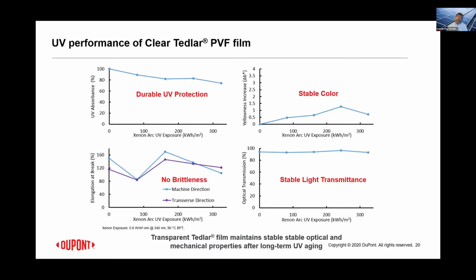So anyway, coming back over here, the film itself doesn't get brittle, again, over 350 hours of UV exposure, and it does not lose the light transmittance that I had shown you earlier over this entire exposure period. So this gives us the confidence that the transparent Tedlar film maintains stable optical as well as mechanical properties after really field relevant long-term UV exposure and UV aging.